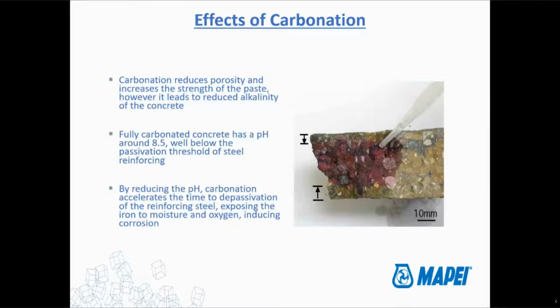So when we're building new structures, we need to keep that in mind so that we can use products that will help delay the carbonation as much as possible, or extend that passivation layer as long as we can, and keep moisture out. Again, all the different technologies that we're going to talk about in the latter half of this presentation are things that we need to be thinking about, even on a brand new structure, because as soon as the concrete is poured, it's basically setting itself up to start corroding sometime in the near future.